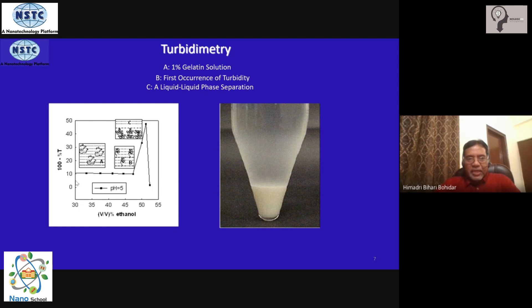And this cartoon tells you how the phase separation is taking place. Most of the aggregates are staying here and few nanoparticles are suspended in the supernatant which corresponds to this. Driving the non-solvent concentration or the organic phase beyond this will ruin the entire experiment and your experiment is dead, which means the turbidity is now here so you have lost all the material to sedimentation. That is a failed experiment.